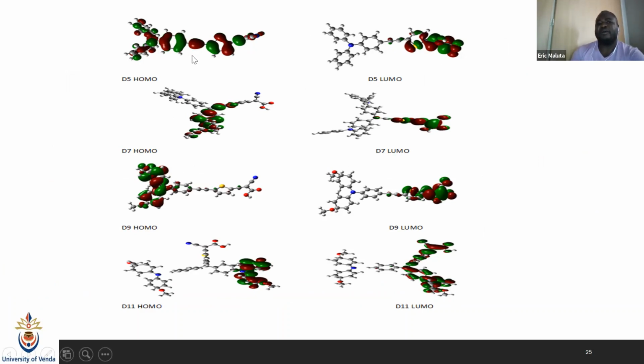We can see where the highest occupied molecular orbital for each dye sits and the lowest unoccupied molecular orbital for each dye sits. But because these dyes are going to be adsorbed on the TiO2 surfaces, then on the combination, the LUMO goes to the Ti, because now we will have the HOMO on the dye and the LUMO on the Ti. Hence, the dye molecule absorbs and then injects into the TiO2.